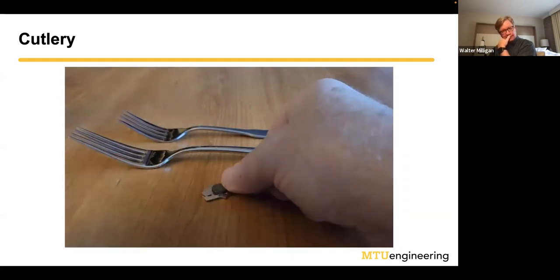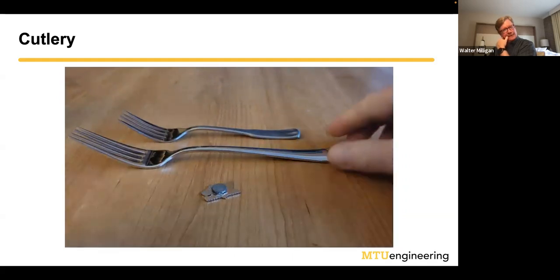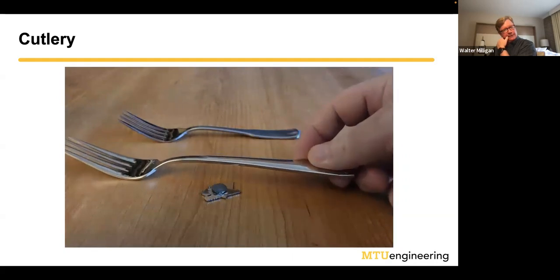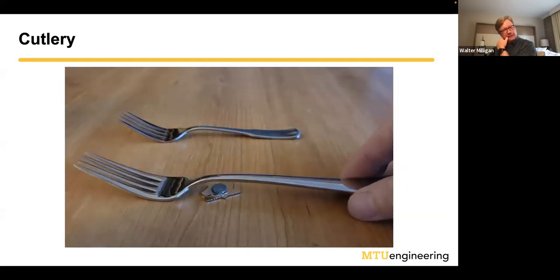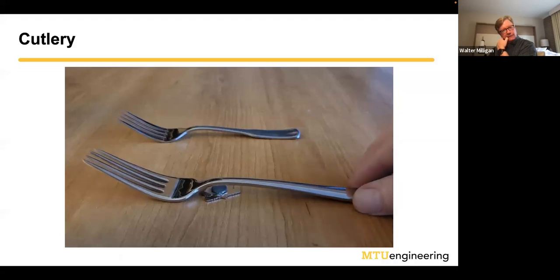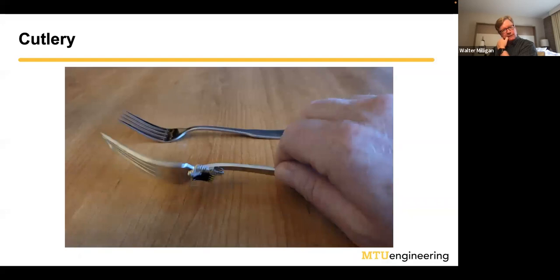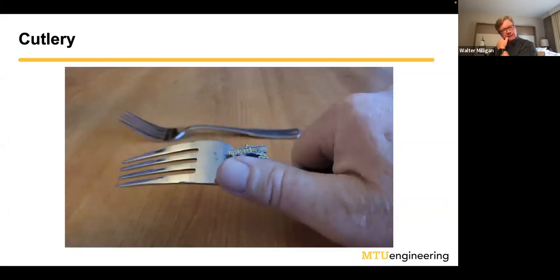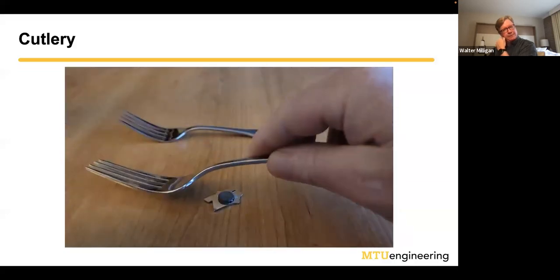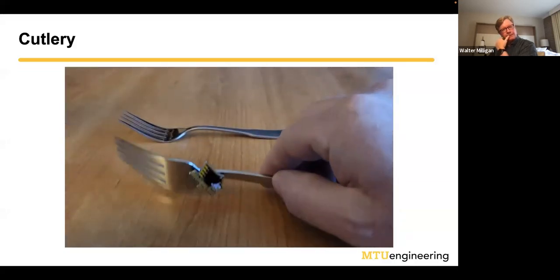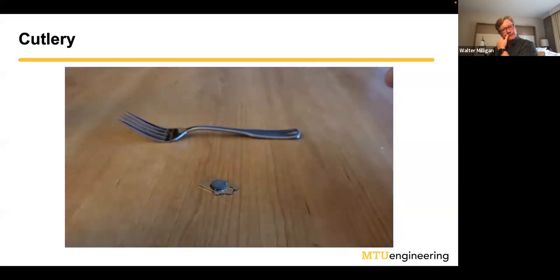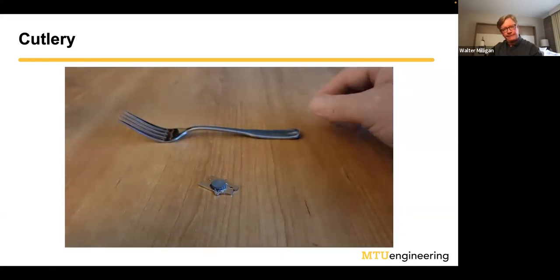Second one here is one that I think I got as a gift in a set. And so this one is much more expensive. And if I put that fork near there, it doesn't fly up until it gets very close to it. And then you can see that even though it is somewhat magnetic, it isn't nearly as strongly magnetic as the other one. And so it kind of grabs on, but not really. Much less magnetic. And in fact, you can put this through a demagnetization operation if you wanted to take the magnetism almost completely out. And that's one thing that they do in industrial operations where they sell austenitic stainless steels.